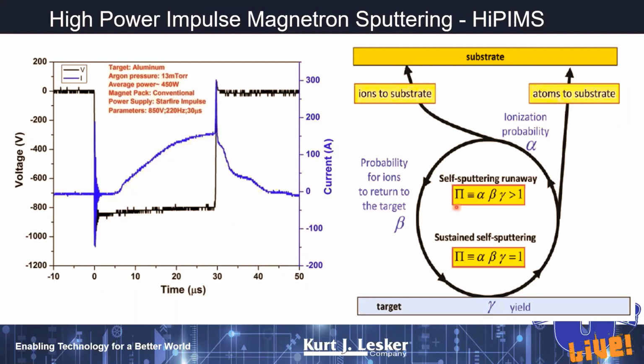And so some materials now, like copper and titanium and maybe even aluminum, we can actually have what's called self-sputtering runaway, so that once we get this cycle going, we have enough sputter target atoms returning to the surface of the target that we're now sputtering purely with sputter target material, and we can actually reduce or maybe even eliminate that argon process gas.